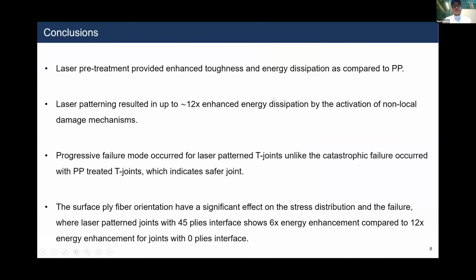So in conclusion, the laser pretreatment provided enhanced toughness and energy dissipation as compared to the peel-ply pretreatment. The laser patterning resulted in up to 12 times enhanced energy dissipation by the activation of non-local damage mechanisms. Progressive failure mode occurred for laser patterned T-joints, unlike the catastrophic failure which happened with the peel-ply treated T-joints, which indicates a safer T-joint with patterning. And also it is worth noting that having a 45-degree surface ply orientation produced weaker toughness as compared to a 0-degree ply orientation, as the 45-degree ply orientation did not have the adhesive ligament phenomenon which happened with the 0 ply. Thank you for your time, and let me know if you have any questions.